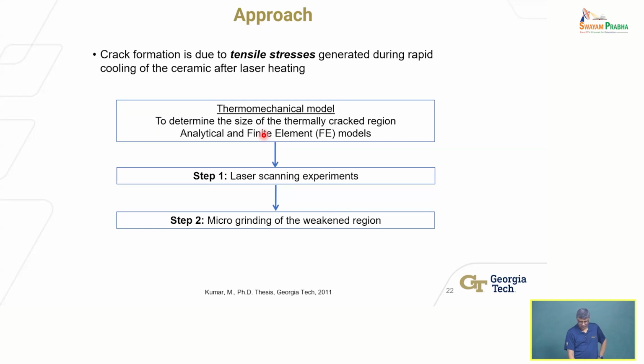So I can use a thermomechanical model. You can do finite element modeling if you want, or there are analytical models that allow you to actually, knowing the energy distribution that you're using with the laser that's irradiating the surface, compute analytically the circumferential thermal stresses or the radial thermal stresses, the different components of thermal stresses. Those solutions exist, right? So we did both in this case. The only advantage of the finite element model is that you can account for boundary conditions more properly if they're more complex, right? But if you're only irradiating a very small region, then you can treat the whole problem as plane strain or plane stress, and you can use analytical solutions. Has some limitations, as we will see, but it serves the purpose though.